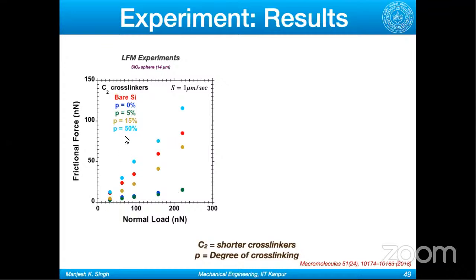And then as we increase the degree of cross-linking, we see higher and higher friction force. If you take the slope, you will get the coefficient of friction, and you can safely say from here that as you increase the degree of cross-linking, your friction force or coefficient of friction goes up. So this is for C2 cross-linkers.